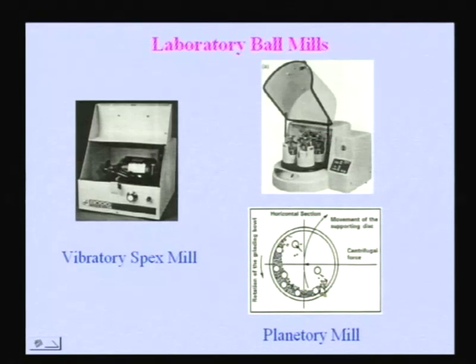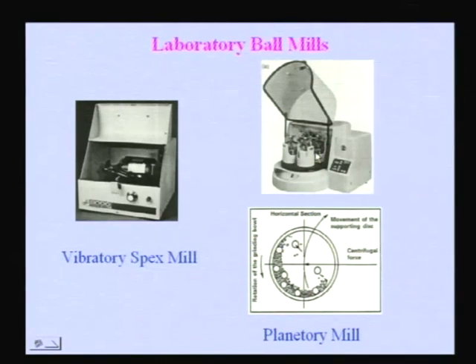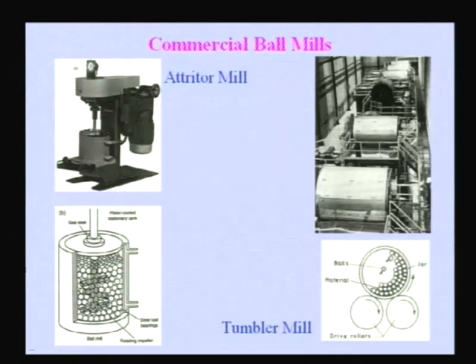And because of this, the balls which are there inside the bowl will get some kind of centrifugal forces, and because of this the balls will hit the powder, and hence you get the energy transferred to the powder. And this kind of ball mills, planetary mills, have a slightly higher capacity than the vibratory mills, and one can go up to about 1 kilo. If you put 4 bowls, each one can take around 200 grams in principle. It depends on the type of materials and the density of the material, because the volume is usually fixed. So, depending on the density of material, one can go up to around 200 grams per bowl. So, approximately about 1 kg one can get. So, these are the laboratory mills.